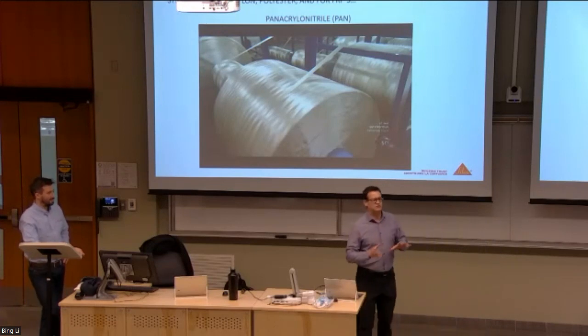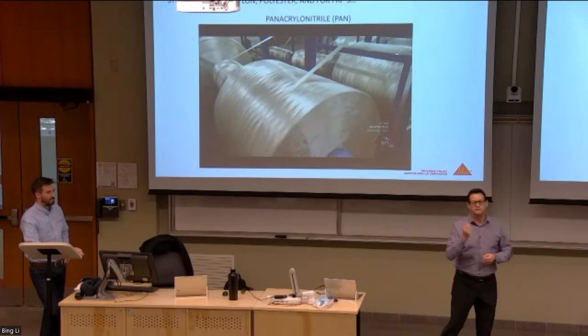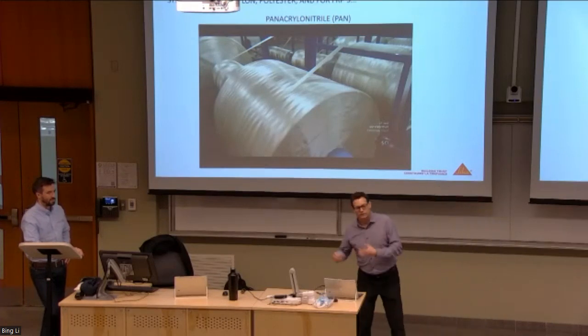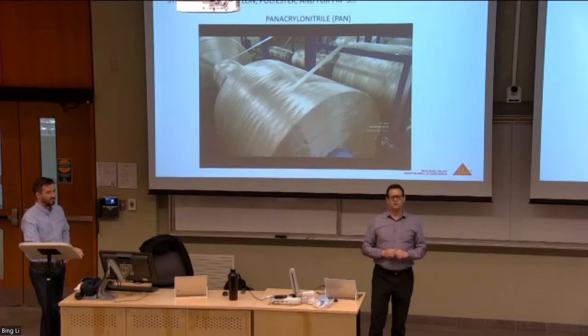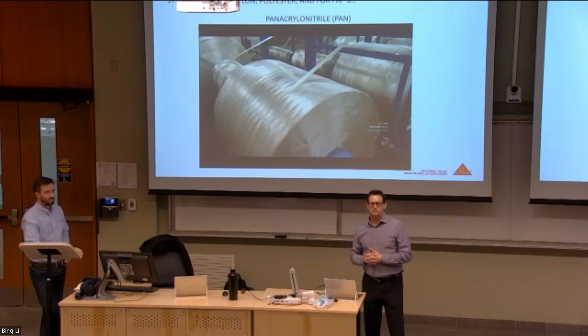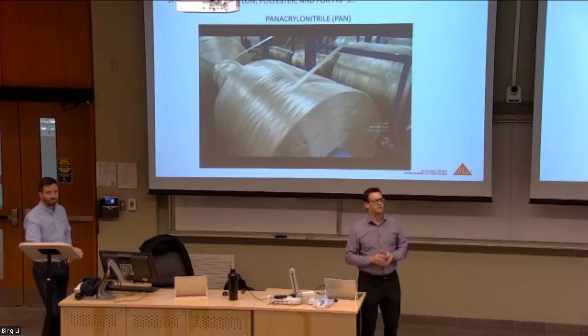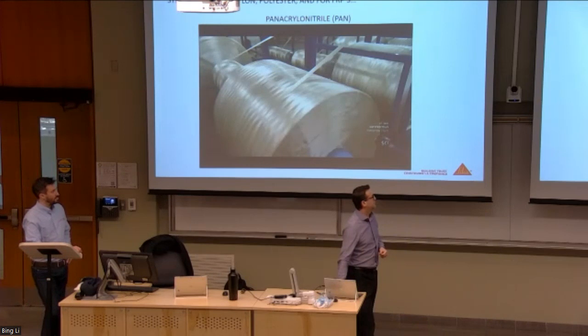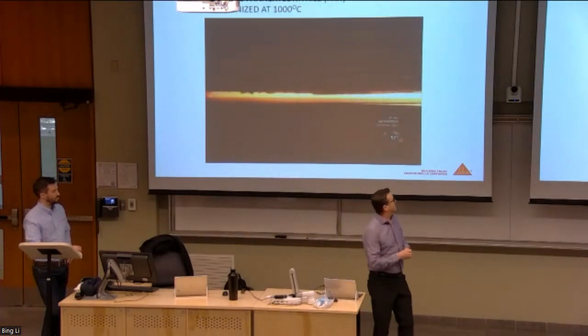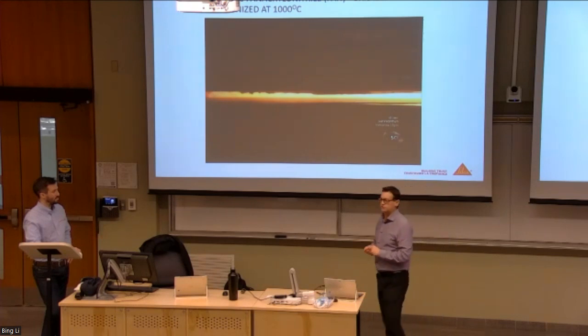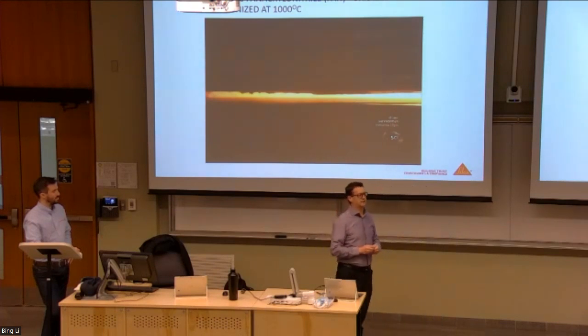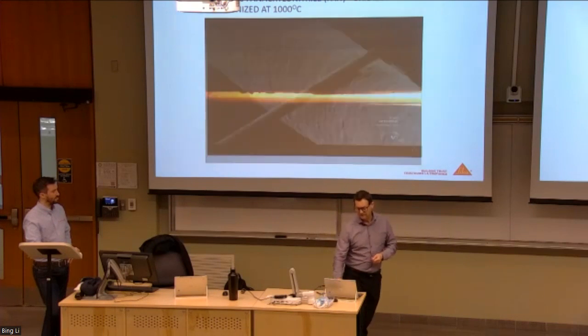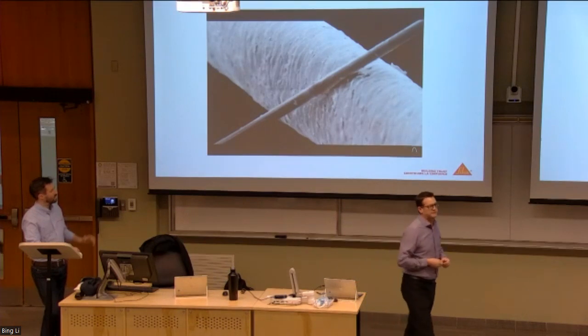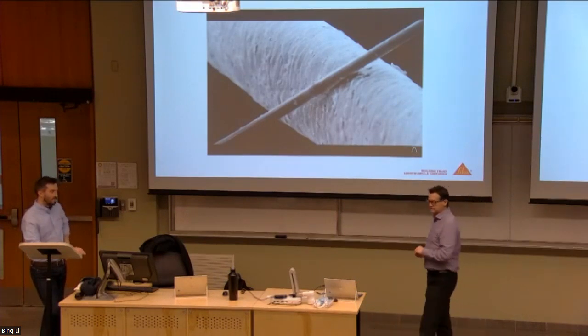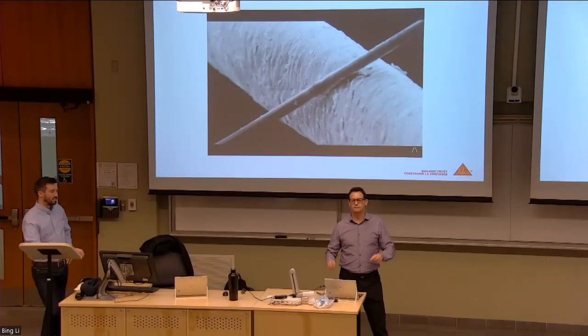There are millions of these individual strands. They're about one-tenth the size of a human hair. When you bundle them all up together and package them in an epoxy matrix, you're yielding something that gives you high flexural strength when you bond it to the underside of, or around, concrete or a column. Once they go from this strand, they go through a heat aging process and they're fired at 1,000 degrees Celsius. These things are cooked. You're changing the properties and strengthening them to a high degree. One individual strand would be roughly one-tenth the size of a human hair.